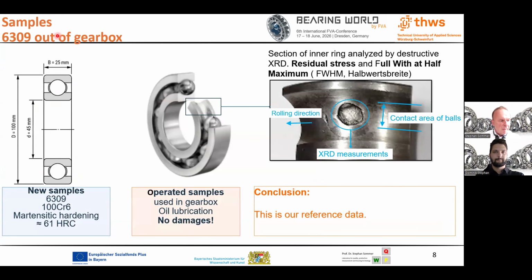Now, how do our samples look like? We are using ball bearings 6309 out of a gearbox application. We have new bearings here, 45 millimeter in bore, 100 millimeter in outer diameter. And the bearings are a standard bearing steel, 100Cr6, with martensitic hardening heat treatment, and it's around 61 Rockwell hardness. And the used bearings are out of a gearbox that were oil lubricated, and they do not have any damages.